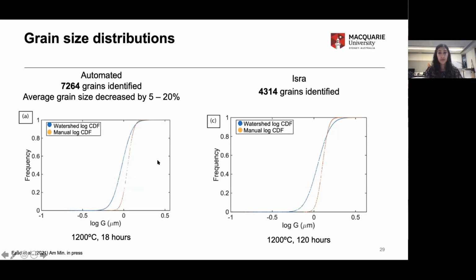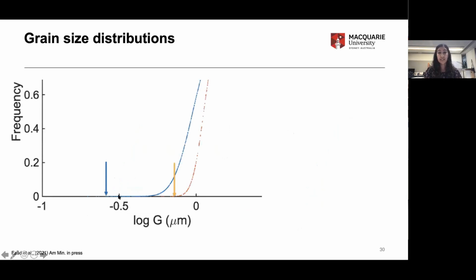This isn't the reason for the reduction in the average grain size though. If we zoom in and have a look at the tails of these distributions, what actually happened was the automated technique in blue here was able to identify far more smaller grains. That suggests that with manual techniques we are either under segmenting our grains or completely ignoring small grains. And that's probably true because measuring grain size by hand is seriously tiring, and after a while, you go for the easiest grains that you can see. It's not easy to find grains which are half a micron big.